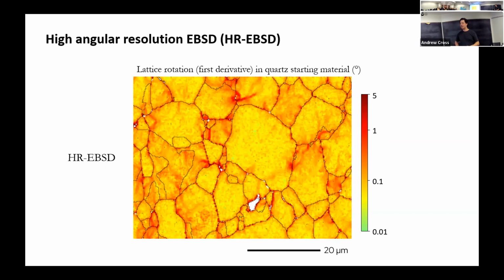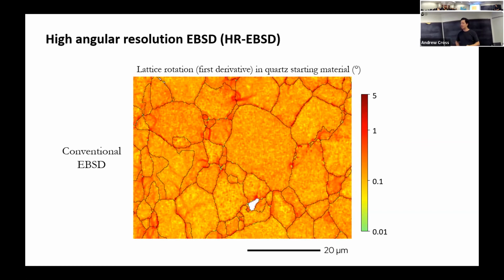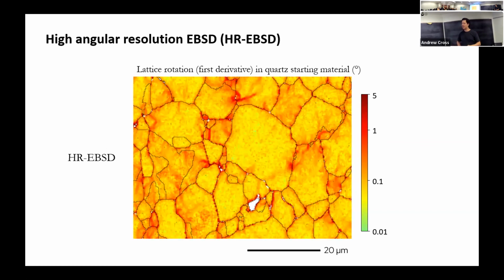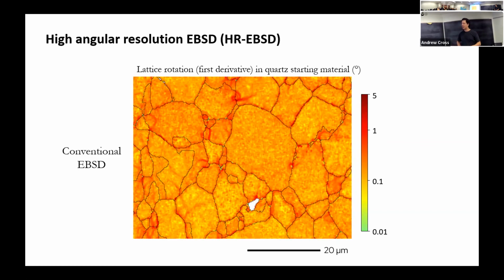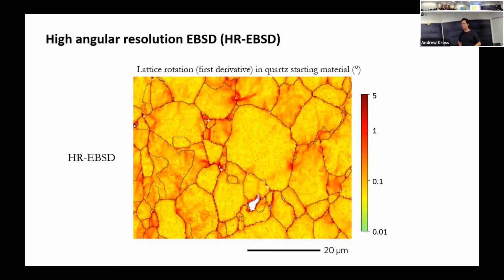If we do cross correlation, now we get an order of magnitude increase in precision, so we're able to pick out features a lot more cleanly. You can see this subgrain wall in here quite nicely. You see another one that kind of runs up here. And down here through the corner of this grain, we've got a subgrain wall. So this corner of the grain is just bent away from the rest of it by a slight amount.